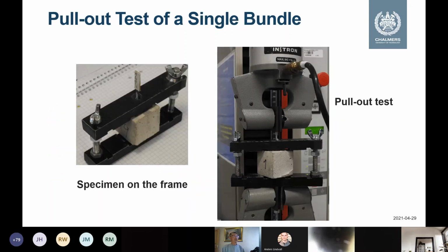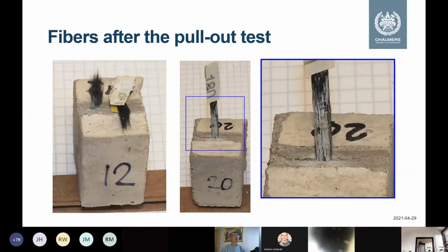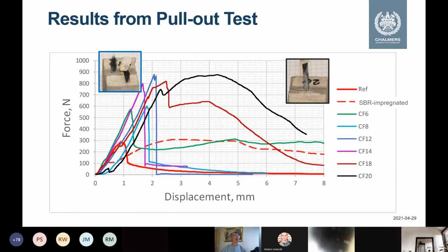Then we developed a method to improve this bonding, by nano impregnation. After nano impregnation, I will show you this single pull-out test. After the pull-out test, you can see the fiber either becomes broken or is pulled out only with great difficulty. So this is the curve.